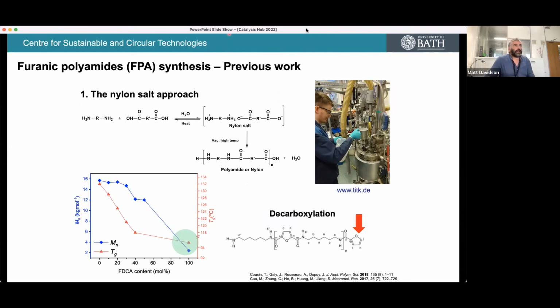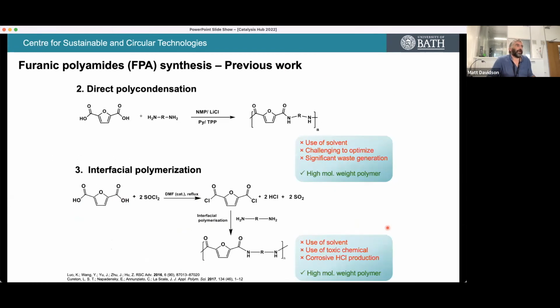In looking at making these things using FDCA as a building block and whatever amine you want to use as the monomer, there's been quite a lot of previous work, but nothing has really looked scalable to date. There are a number of approaches here. With the nylon salt approach, you typically only get low molecular weights, because of decarboxylation that can take place. It is one of the major disadvantages of this approach. So high molecular weight polyamides have never really been made this way.